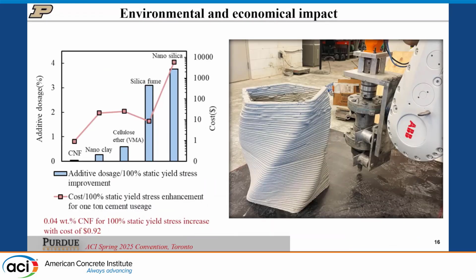The last thing to talk about is the cost of this and its effectiveness. We wanted to normalize our study and look at how much rheological additive you need to achieve twice the static yield stress, a 100% increase. What you see here is that with CNFs we're able to achieve that at almost 0.04% of the weight of binder, which translates to a cost of 0.92 US dollars, not Canadian dollars.